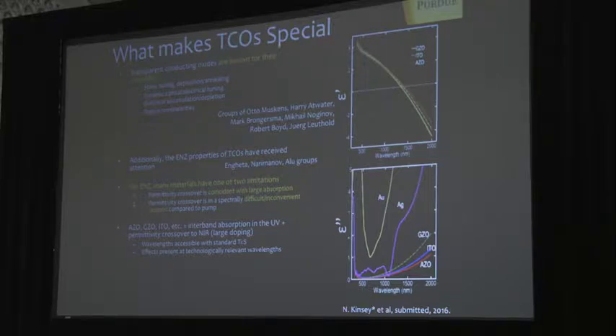Speaking of another important class of new plasmonic materials, we're excited about these transparent conducting oxides. There are several groups working in this area, and they really show spectacular properties. First of all, they're easy to make. You could really tune and switch their properties dramatically. They're non-stoichiometric. You could change their plasma frequency over a very broad spectral range by simply changing the conditions of making them. And the way to make them is very cheap, and they show very unusual properties. Those properties, as I will point out, get really interesting at the point when epsilon prime crosses zero. This is the so-called ENZ point, epsilon-near-zero point. So that's for these transparent conducting oxides.